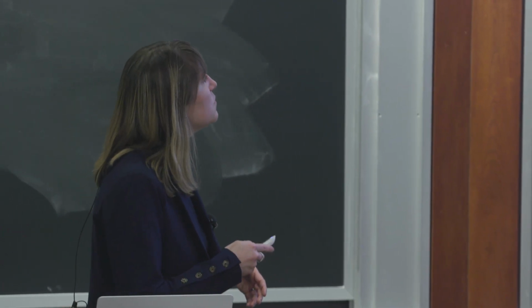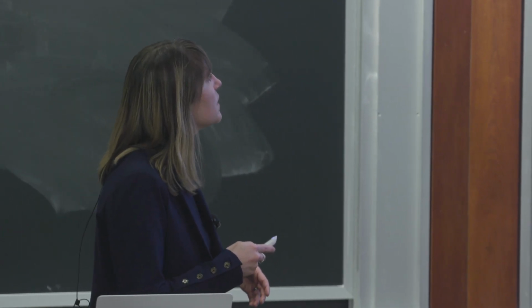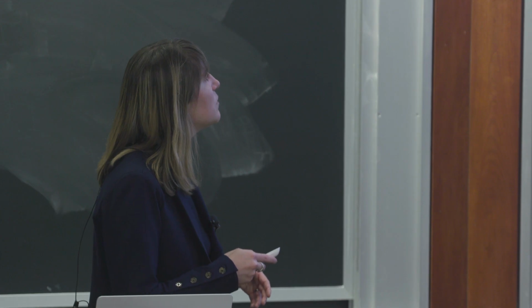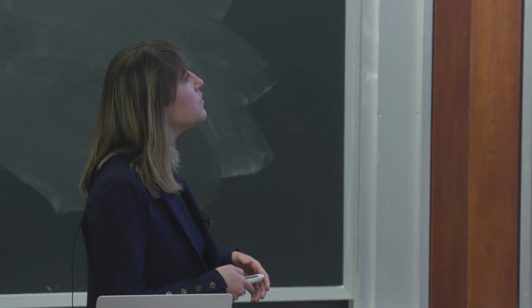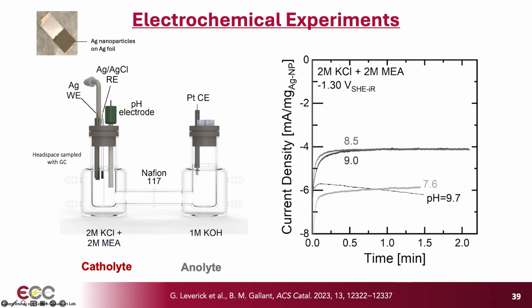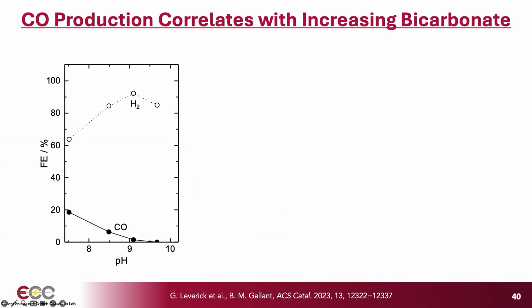The catholyte is 2 molar of an amine, 2 molar of a supporting salt, KCl, and the anolyte is 1 molar KOH. We have a Nafion membrane in between. And typically we're applying a constant reducing potential, so we're doing chronoamperometry. And as I mentioned, we're using pH as a variable here, so we bubble to different CO2 partial pressures and then look at the outcome.